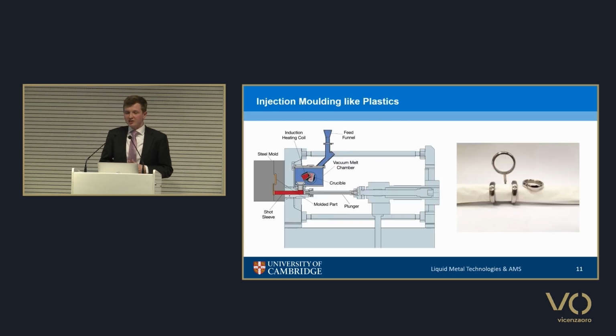So in terms of processing, Ulrich talked in great detail about investment casting, but there's also this advantage that because metallic glasses are so much like polymers, there's a process very analogous to plastic injection molding. And there's several companies that are able to do this. And the key advantage is time. As you all know from Ulrich's talk, we have minimal shrinkage on casting, and we have very good surface finishes. And so we can actually cast rings in matters of seconds, as opposed to the relatively long time for investment casting.